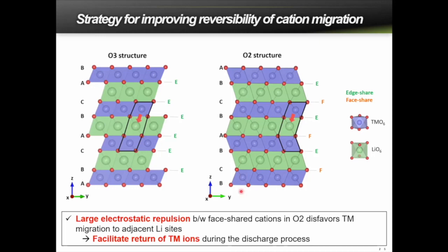So we believe that we can control this transition metal migration by altering the stacking sequences of the layered structure, from the conventional O3 structure with ABC, ABC stacking to the O2 structure with ABCBA. So it seems like the same layered structure, but the oxygen stackings are different, so that the local transition metal environments are quite different.